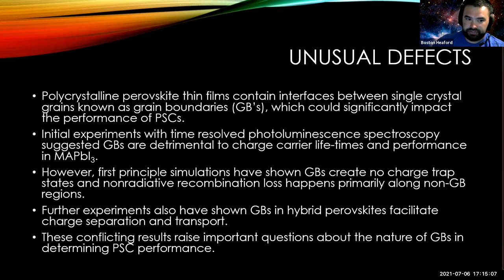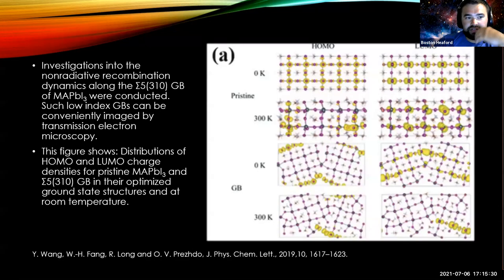And other experiments have also shown that grain boundaries in hybrid perovskites actually facilitate charge separation and transport, which conflicts with some experiments. So they raise a lot of questions about the nature of grain boundaries in determining perovskite solar cell performance. And so some investigations were carried out into the recombination dynamics along the grain boundaries of methylammonium perovskites. And this is just a depiction of the perovskite at pristine and grain boundaries at different temperatures.